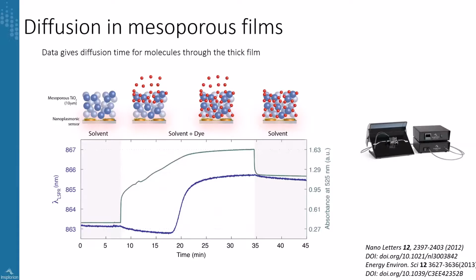And curiously, once the dye concentration starts to stabilize is when you start having the plasmonic peak change, is when the NPS signal starts to kick in. And this makes sense because once the solvent starts to stabilize, it means the film is becoming saturated, and of course that's the time when it's reaching the bottom of the film, so exactly when it's reaching the surface of the sensor. So of course that's when NPS is more sensitive, that's when we start getting the signal, and of course the signal stabilizes fairly quickly, and once both NPS and the dye cannot go any further, they're both stable,